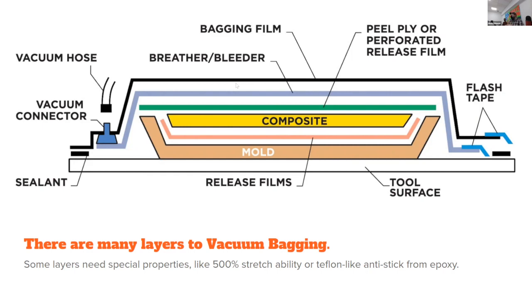If you get a perfect seal in your vacuum bag, in theory, you can pump out all the air and then leave it, but that's pretty much never how it's worked for us. So we just leave it for the minimum number of hours to hit like half the pot life, and then we can walk away and turn it on. Yeah, it'll be fine. Or half the cure time. So on Thursday, we'd start our thing, and then we'd let the pump run until Friday, midday, Friday lunchtime. That's the game plan.